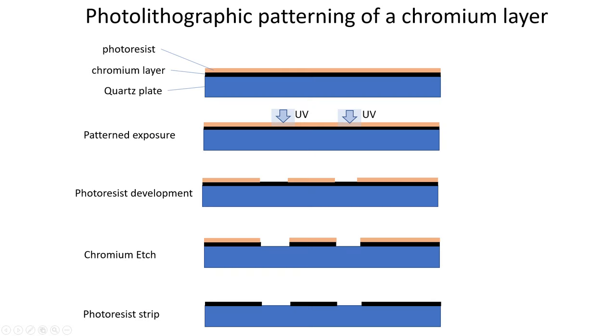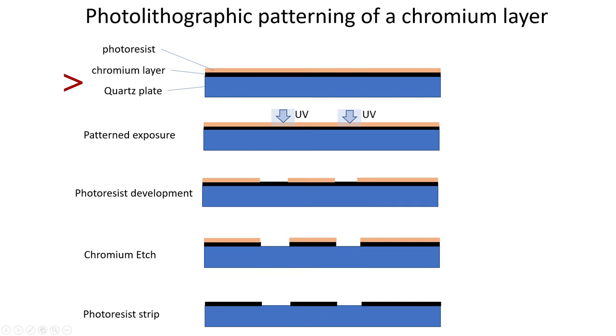My plan was to make photon sieves hands-on and find out what they are all about. As a basis I used old photolithography masks — quartz plates with a chromium layer on top, which is non-transmissive. To make the photon sieves, I just had to etch tiny holes in the chromium layer. I spin coated a layer of photoresist on top of the chromium layer, then exposed the photoresist in the photon sieve pattern, developed it, etched the chromium, and stripped away the photoresist, leaving the mask with the photon sieve pattern etched in it.